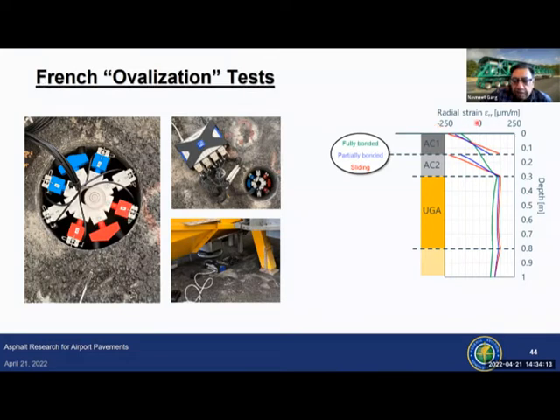And if you look at the figure on your right-hand side, if the two layers are fully bonded, then you'll have a continuous strain profile as shown by this green line. For partially bonded lifts, you start seeing changes in the strain magnitudes and the nature of the strain changes. And once you have a sliding surface or no bond between the two layers of the interface, then you have big differences in the strain magnitudes, and one is compressive and the other one is tensile in nature.